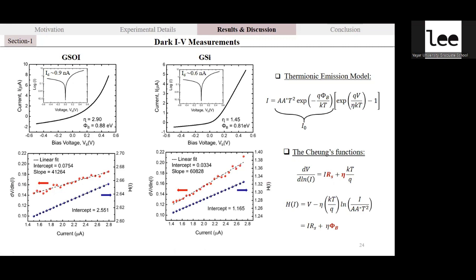When we look at the electrical characterization of these two different device structures, here you can see the dark current of both structures is very low, which is required to work with high performance photodetectors, in the nanoampere scale. The ideality factor and the Schottky barrier height of the devices were determined by the thermionic emission model equation, and then by using Cheung's functions, we observed the series resistance and the ideality factor of the devices. Here you can see that both devices have rectification behavior.